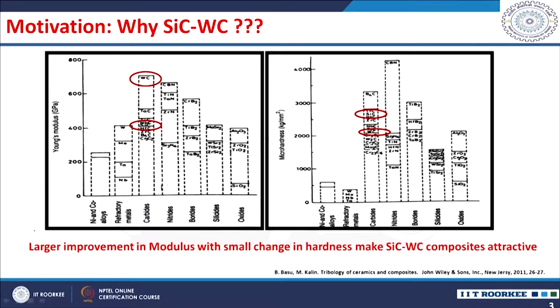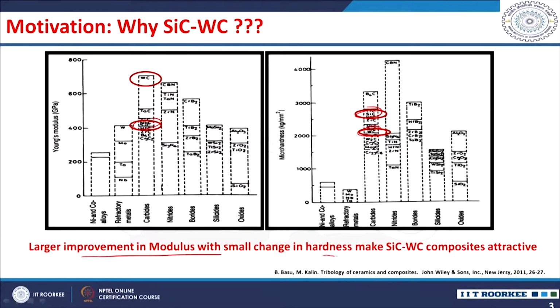Among the silicon carbide based ceramic composites, we can see the Young's modulus of tungsten carbide is much higher than silicon carbide, whereas the hardness is slightly lesser than the silicon carbide hardness. So, if you have a silicon carbide tungsten carbide composite, we can expect an improvement in the modulus with a small change in the hardness. Such a composite will be attractive for several tribological applications.